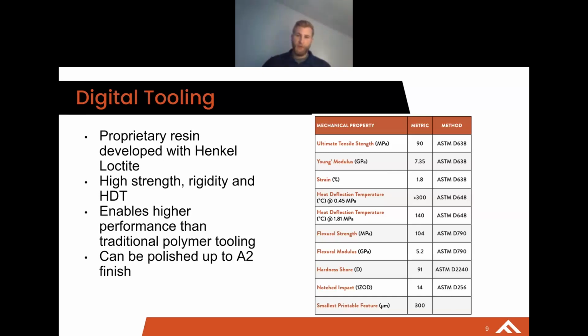So we're seeing performance in temperatures above 700 degrees Fahrenheit. We just haven't tested the HDT test that high yet. So we know it lies somewhere above 300C, but we're not quite sure where. And I'm not sure that there's going to be any testing going into that, as we haven't seen really any need for it. So along with that high strength, rigidity, and HDT, enabling that higher performance than traditional polymer tooling, another key factor for digital tooling is that it can be polished up to an A2 finish.